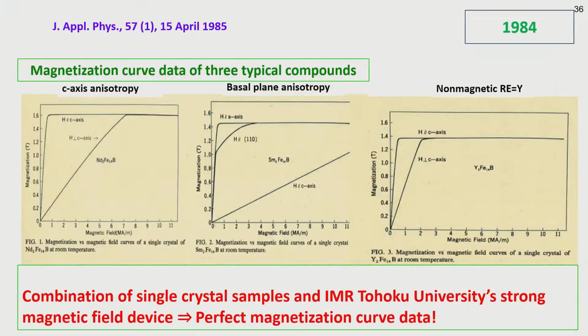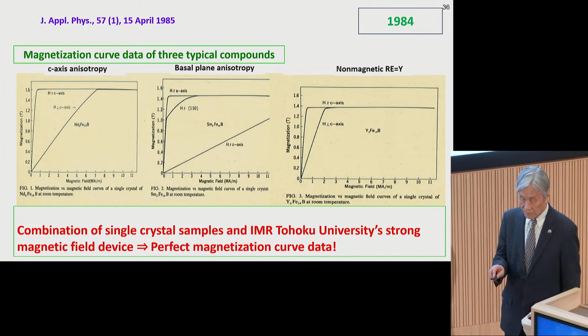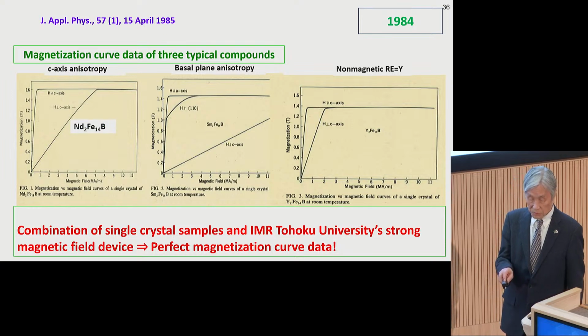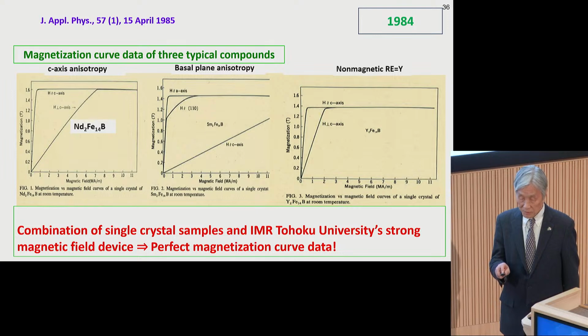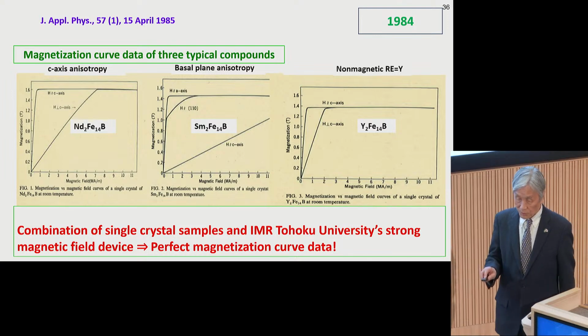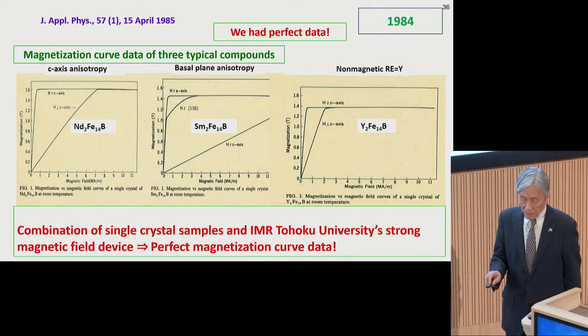Okay, so these are the magnetization curves of 3 typical compounds. Combination of single crystal samples and IMR Tohoku University's strong magnetic field device, perfect magnetization curve data were obtained. Neodymium 2 iron 14 boron, this is a typical compound with C-axis anisotropy. And this is a typical compound with basal plane anisotropy, samarium 2 iron 14 boron. And yttrium 2 iron 14 boron. This is a typical compound with non-magnetic rare earth. So we had very basic data completely. We had the perfect data.